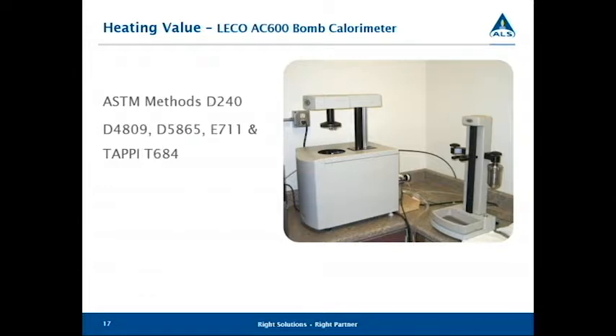So the first test and the primary test we do is heating value, and this is performed on a bomb calorimeter. The old systems weren't automated like this. This is fully automated, and it's very, very accurate. Typically, our QC results on this instrument are 99 to 101% recovery. They're very, very accurate.